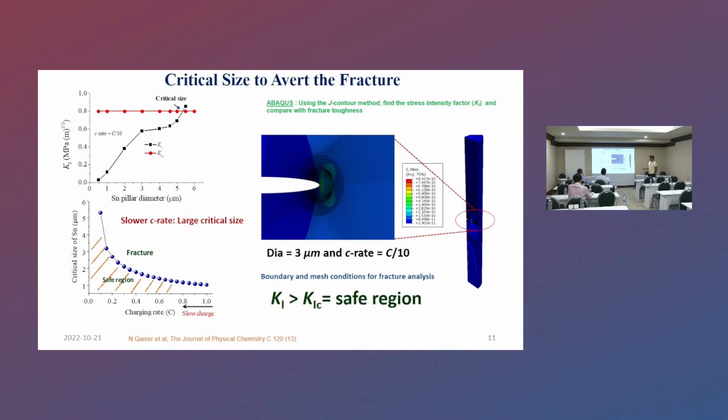Another factor, for example for the battery case, is the critical size, or the safe area where it will not crack after lithiation. So we call it the critical size to avert the fracture. I used Abaqus software and induced a crack on purpose, and then we can calculate the values of the stress intensity factor, and then compare with the fracture toughness value, and that will dictate the